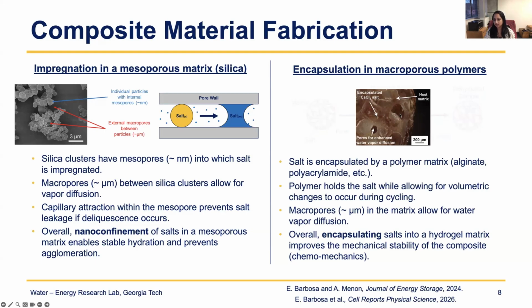So here, this is with an alginate matrix. And you can see these large pores for water vapor transport. And then you can see the small white particles that are embedded inside the matrix. And that is essentially the salt. And so this is another way of stabilizing the salt into a composite. And this allows us to cycle it over several charge-discharge cycles. So this is some of the work we're doing on the materials level.